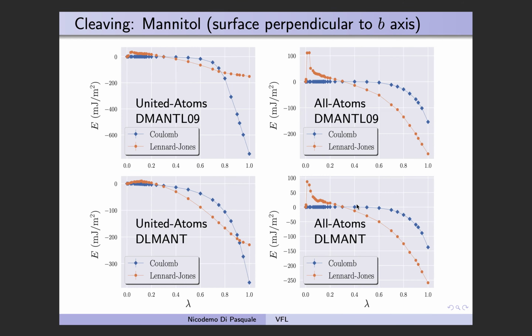Here we can observe the kind of results that we obtain, that is to say the thermodynamic path, the integration of which gives the surface free energy. As can be observed, they are all different for the same orientation when using different models and different experimental lattice parameters.